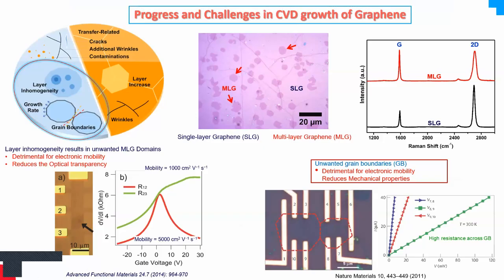And the second important thing in graphene growth is we want a single crystal one. We don't want to make polycrystalline, because once you have polycrystalline graphene, the grain boundaries act as scattering sites. It can affect the electronic performance as well as optical properties. So these two challenges are very important. One is to get single layer graphene exclusively, and second, to avoid any kind of grain boundaries to grow single crystal graphene.